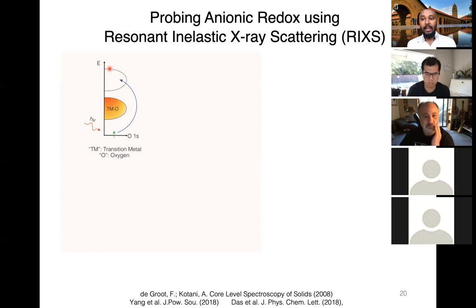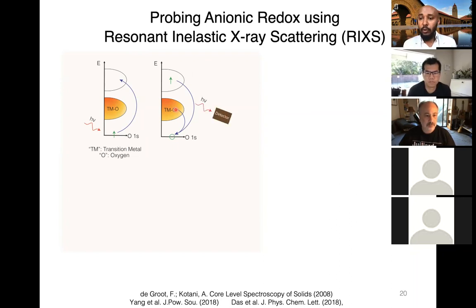This is the first step, and that leaves an intermediate state that is not stable. Therefore, in the second step, this electron that's excited and other electrons in the occupied orbitals will jump in to fill in the core hole. To conserve energy, this jumping process will emit a photon that can be collected using a detector.